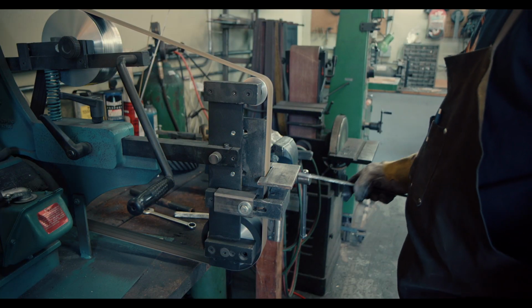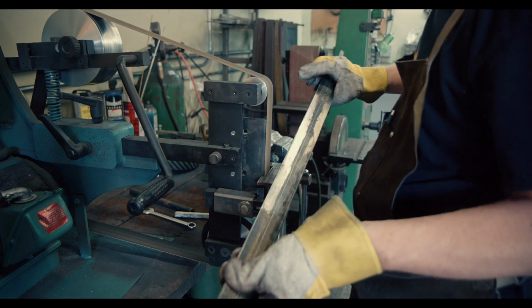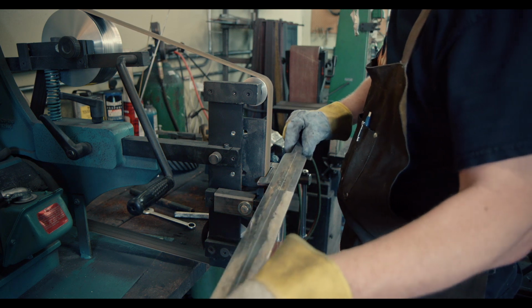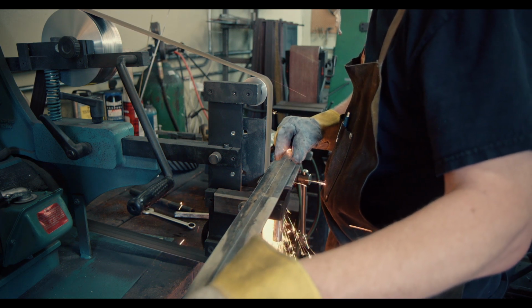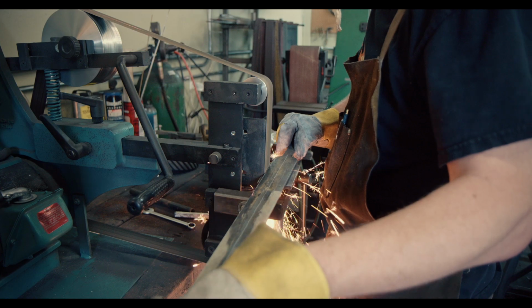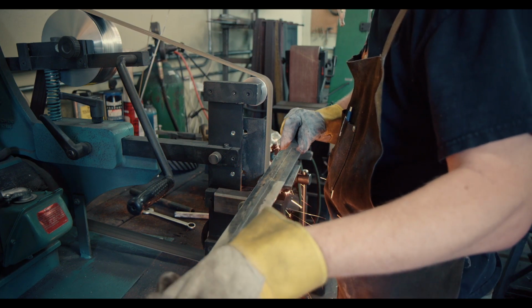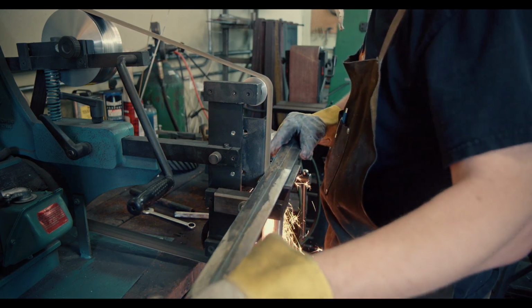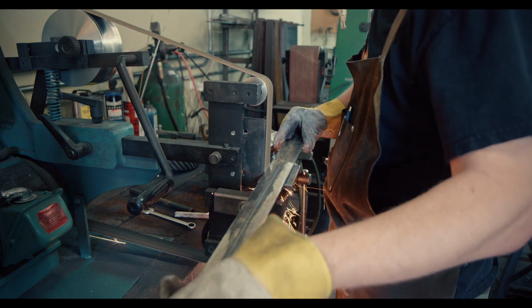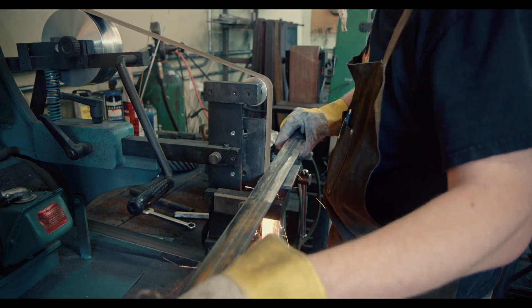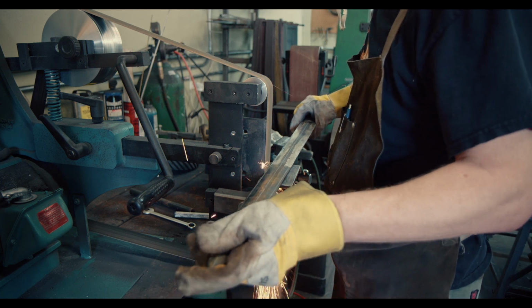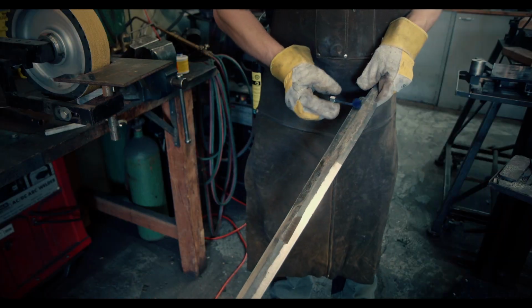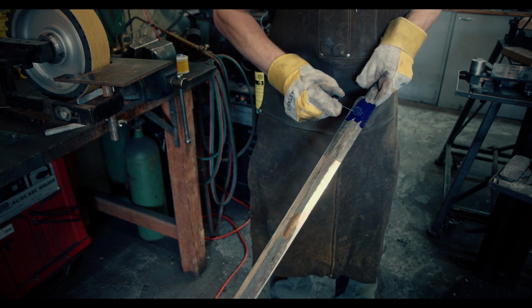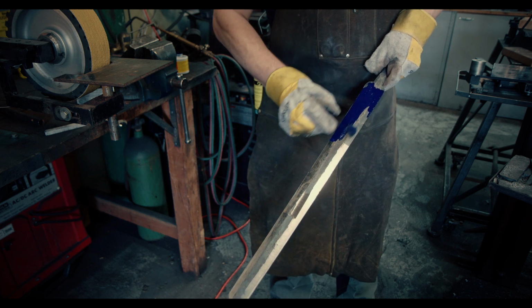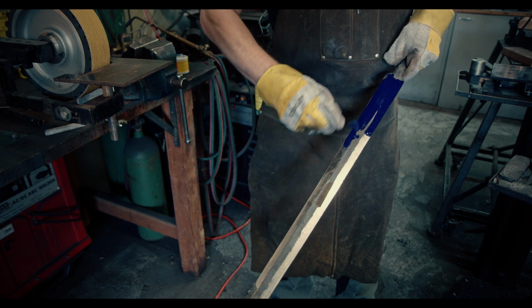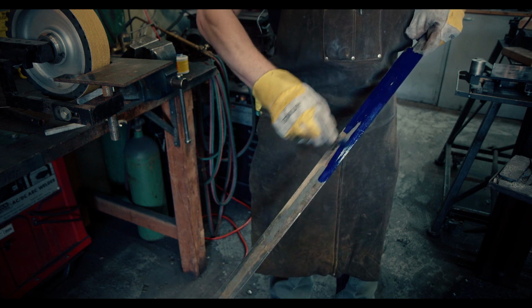The carbon atoms can have different arrangements in the steel. There are roughly three: pearlite, austenite and martensite. At the gross oversimplification, soft steel contains pearlite. When it is heated above its critical temperature, it transitions to austenite, and quick cooling arrests the carbon atoms so that the steel forms martensite. Martensite is hard, and that's what we want to get for the edge of the sword. However, the transition to martensite is quite stressful, and if not done carefully, can destroy or terribly warp the sword.